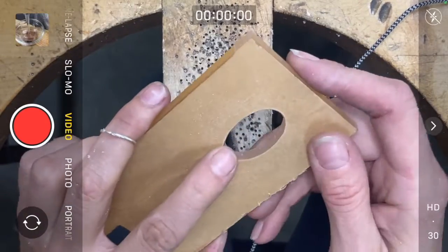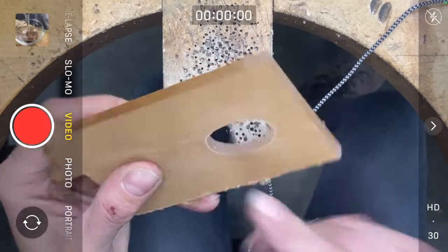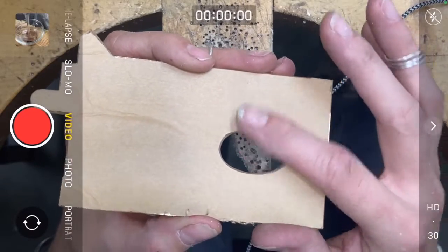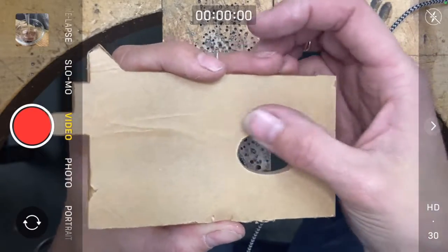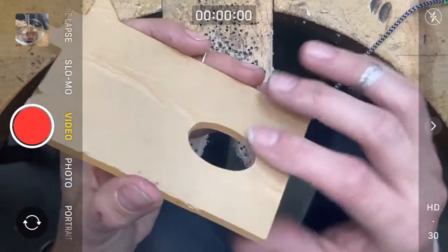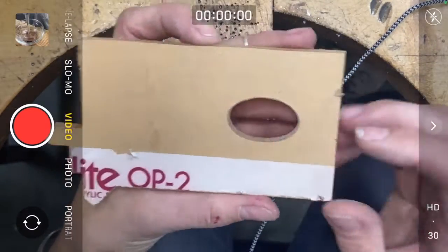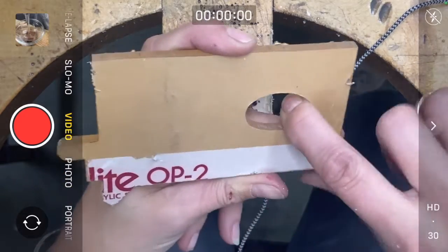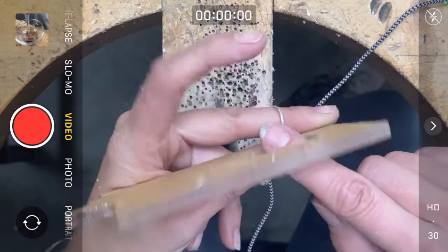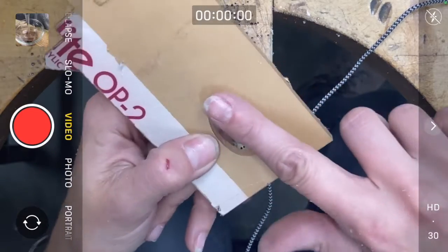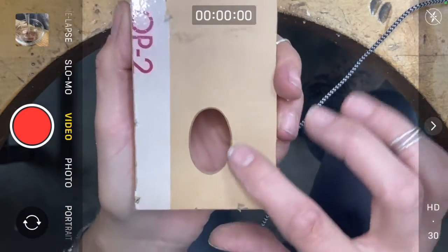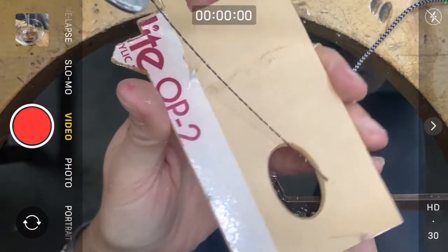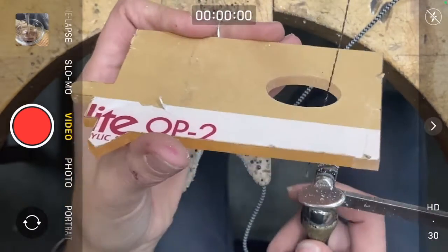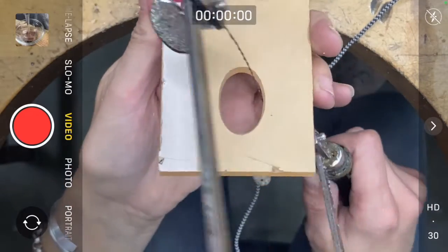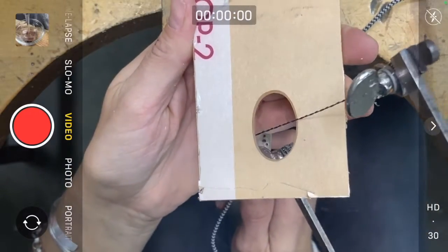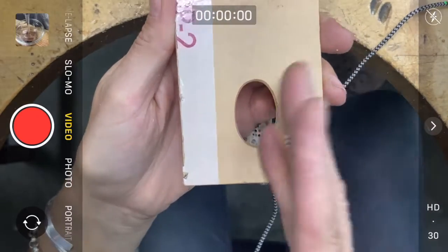So this die was cut out and then filed and sanded to remove any sharp edges to make sure it doesn't get hung up on the metal or rip the metal. The last thing you would want is to rip your metal every single time you'd form with this die. The other thing I did was make it nice and smooth inside, because the texture that the metal is going to pick up on is the texture of the die itself. So you want to make sure not to change the shape. And one thing to be careful of when you're cutting the die is to make sure you're cutting perpendicular. If you're not cutting perpendicular and you have the saw at an angle this way or this way, then your die isn't going to be perfectly perpendicular.